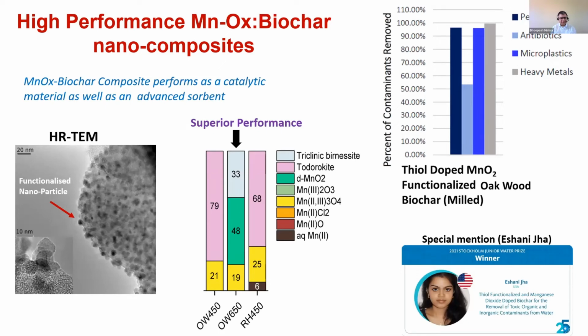That was OW650, and we also did high resolution TEM, and we were able to see lattice fringes on these. A special mention to Eshani Jha, who was a high school student at that time and contributed to this part of the project. She was also a winner of a Stockholm Water Junior Prize. She was able to show that this material can have very high removal of heavy metals, including cadmium, lead, mercury and arsenic, and also pretty high microplastic and pesticide removal. The antibiotics removal was not that high, but it was not too bad either.